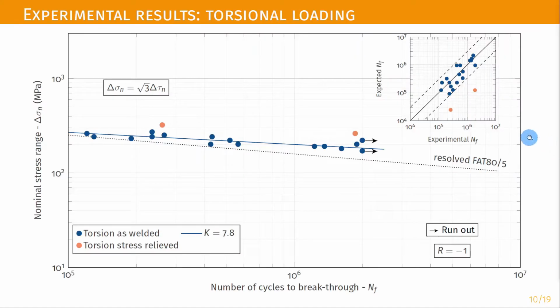In the following, I will present experimental and numerical results for the tube-to-plate welded joint. Experimental results from pure torsion fatigue tests are shown here, specifically for as-welded and stress-relieved specimens. The nominal stress range is shown over the number of cycles to breakthrough. For the sake of clarity, the FAT curve is also shown in order to have a comparison with the standard.